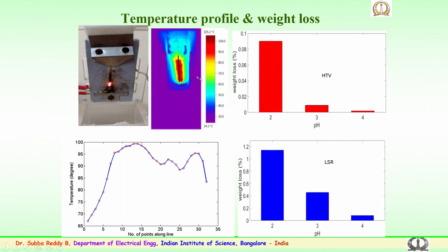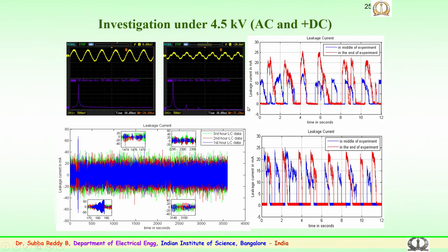This shows a typical thermal imager photograph showing the variation of the temperature profile on the surface. This shows a number of points and the temperature at different locations. These are for two types of samples. One is for high temperature vulcanized, the second is for liquid silicone rubber. Over a period of time after the experimentation, the weight loss of the sample has been measured for various conductivities, and it was observed that as the conductivity or the pH increases, the weight loss is as shown here. So, this is how the performance, particularly for the inclined plane arrangement, has been done.